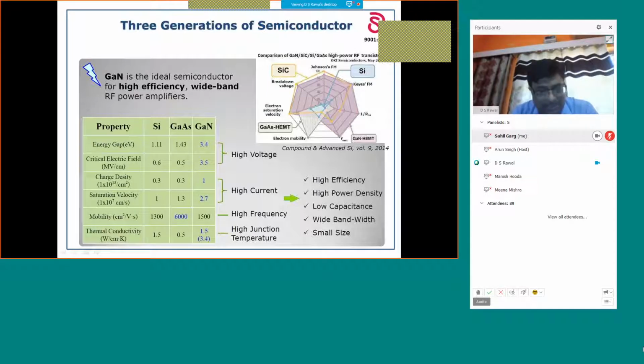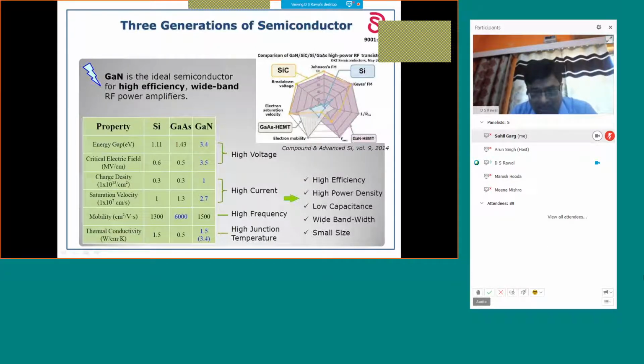So on the first day, as Professor Dipankar Saha categorically mentioned, high frequency performance is mainly because of the high saturation velocity. Normally, people give a lot of value to the high mobility. High mobility is important, but high mobility helps us in reducing the excess resistances and helps in increasing the current density. So although high mobility is very important, for high frequency, saturation velocity is more important. But the mobility reduces excess resistances, source resistance, drain resistance, and in a way, it also enhances the frequency performance.